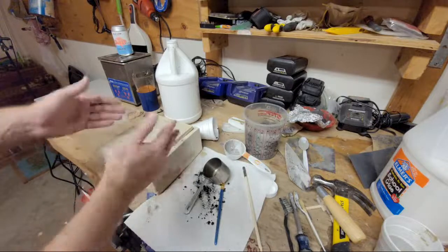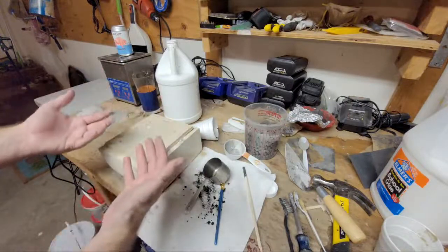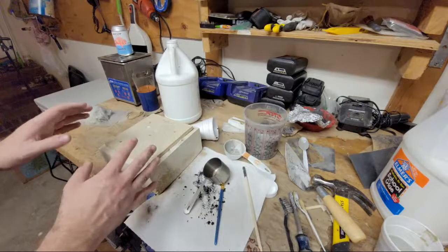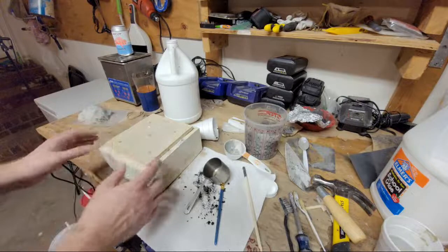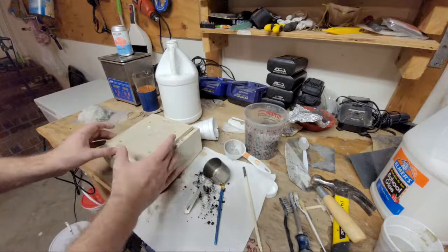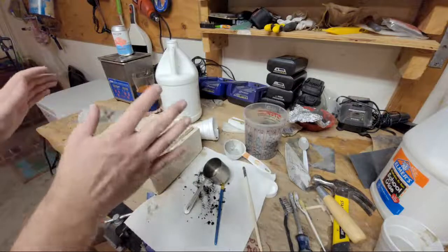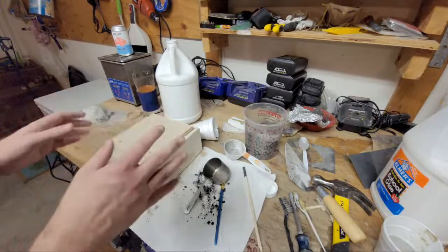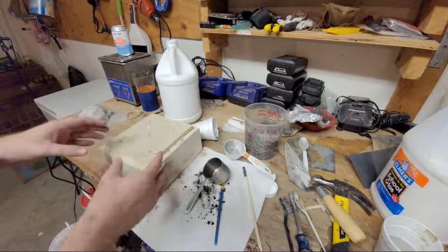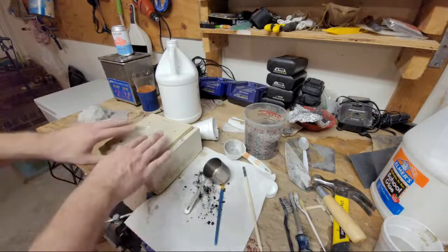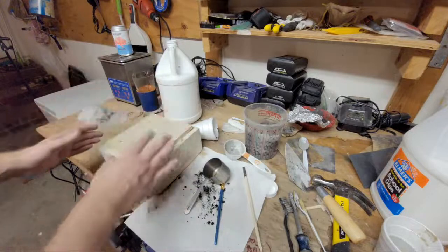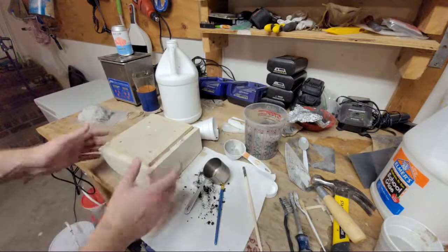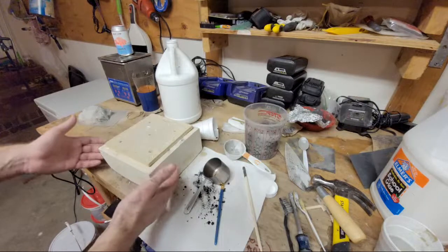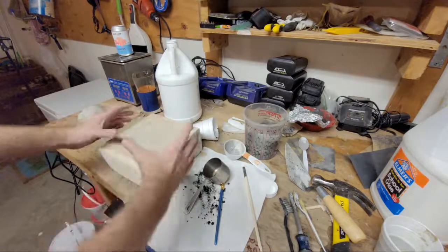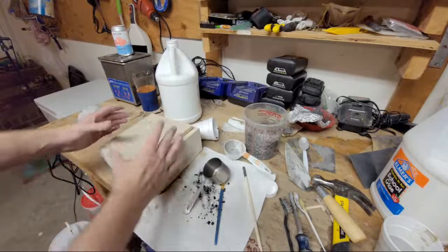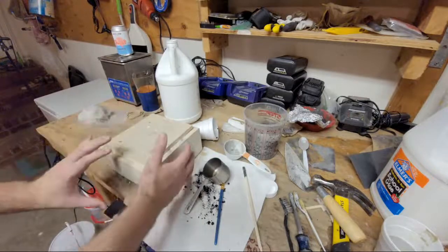These holes should allow for the degassing that's going to take place during the debind. And debind, again, is near the 400 to 800 degree Fahrenheit mark, which burns off the PLA-equivalent binder that is holding together the metal powder, and that'll let that escape. When the temperature reaches high enough for the charcoal, the carbon ignition, that will burn, scavenge any oxygen within this crucible, and protect our part from oxidation.